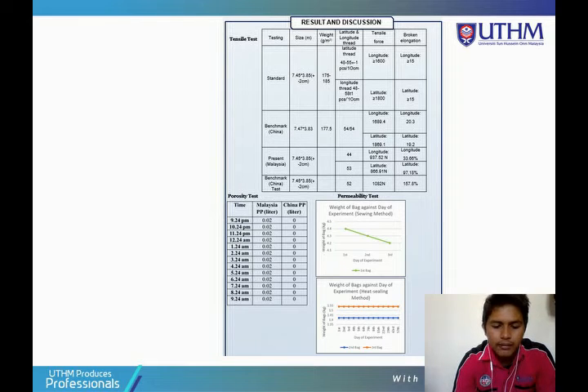The situation can be explained as the sewing method cannot contain water inside the LLDPE bag because of the small pores created between the sewing part and the LLDPE material. The small particles of water managed to escape through the pores created from the sewing part but not through the material itself, as the leak was spotted only in the area of the sewing part. The deduction is supported by the fact that with the heat sealing method, there was no leakage observed, as the seal part and also the entire base were dry even after 2 months of exposure under the sunlight.